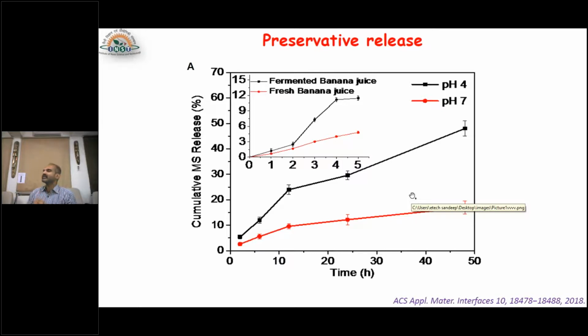Now coming to the application, we have to check whether the material is able to release the preservative. So we put the material in neutral buffer as well as acidic buffer. At pH 4 you can see a 4 times increase in the release, whereas only 10% of the salicylic acid is released at neutral pH. And we allowed the banana juice to ferment for some days. After it reached pH 4, we added the composite material to the fermented juice, and we were able to see the same amount of release in 12 hours. After that we didn't follow it for 15 or 50 hours, because it gives a pungent smell.